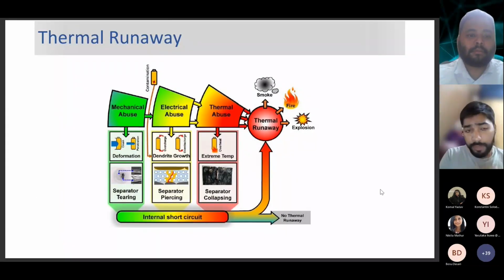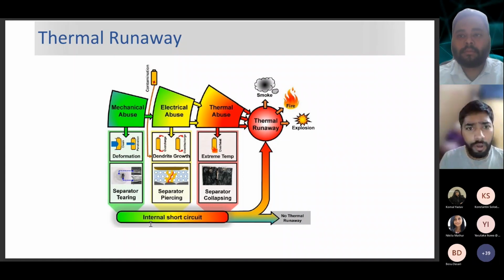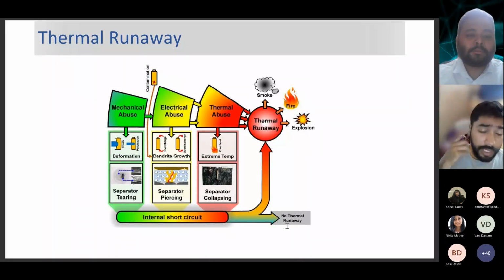So what the previous thing results in, as I said, is basically thermal runaway, but it could be a result of either of these situations. It could be because of some mechanical abuse happening to the cells, or some electrical abuse, something like a dendritic short, or it could be a thermal abuse because the environment of the battery pack has gotten hot, and eventually it leads to an escalated temperature at every scale. Higher temperatures give rise to a higher rate of reactions, and that eventually leads to thermal runaway as well. So it could be mechanical abuse like a puncture, or electrical or thermal abuse. Either way, it's going to lead into a thermal runaway. In some battery chemistries, there can be a short circuit but it may not eventually catch fire. Next slide.